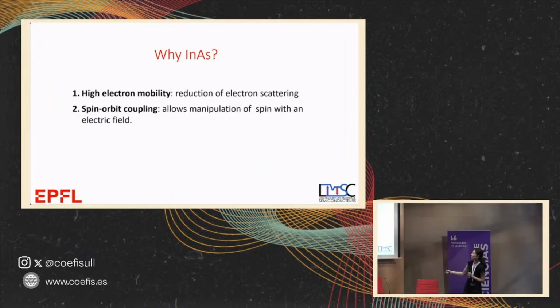The second thing is that you need a material that has spin-orbit coupling, and this is typically materials that have very large masses, which means that there is a coupling between the magnetic moment and the momentum that the electrons have, which means that the momentum is how you accelerate with electric field, for example. It means that you can modify the position of the spin of the electron with an electric field. This is really cool, and if you want to do quantum technologies, you want to have this handle to manipulate the spins with an electric field. So that's why we use indium arsenide and not gallium arsenide.